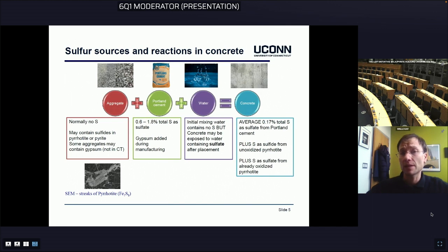Underneath you see, for example, an SEM picture of a pyrrhotite aggregate where the light gray streaks are pyrrhotite. Portland cement can also contain sulfur as a source of the calcium sulfate as gypsum added to the cement during manufacturing. So we need to be careful of this when we test for the total sulfur of the concrete, that we are aware that some part of the sulfur comes from the cement as well.